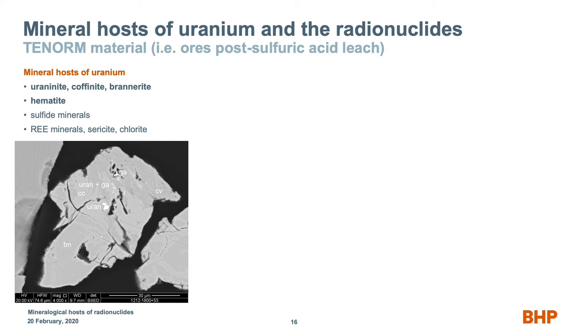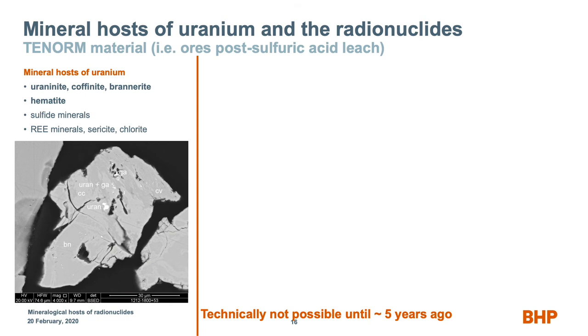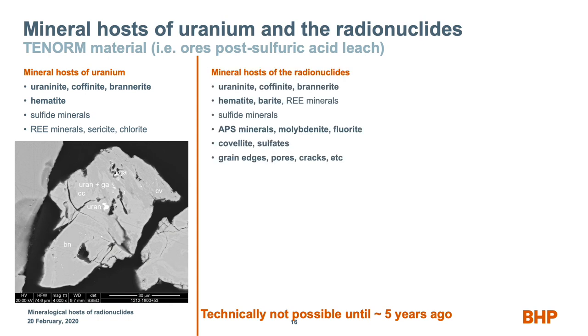And again, it's no longer in secular equilibrium, but the uranium in concentrate occurs as uraninite, coffinite, brannerite, hematite, and sulfide minerals, the same thing that it does in the ore before it gets concentrated. This is a sulfide particle, and there are some holes in it, and those were former uraninites. But again, there are all kinds of little bright white spots on it. We can see that, but I can just tell you that's where uranium is. I can't tell you where the radionuclides are. Looking at concentrate leach, we see the same suite of minerals host the radionuclides that we saw pre-leach, but then we also start seeing other things. And the other things are things like covellite, sulfates, grain edges, pores, cracks, everything that we create during our milling and acid process. Actually, radionuclides start attaching to that.